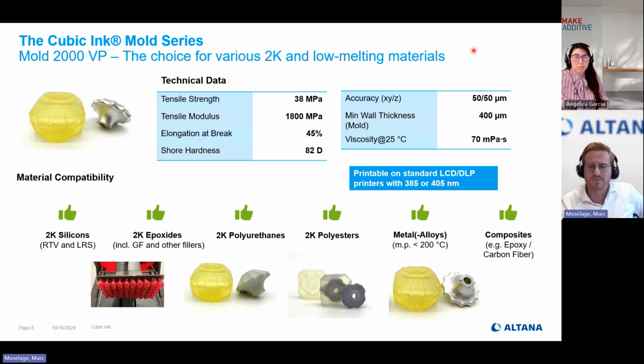Top right, you see some key performance indicators. So the accuracy of the final part, not of the print, is pretty good: 50 micrometers in XY and in Z. The Z accuracy is basically determined by your printer and the layer you print with. 50 micrometers are standard. 100 micrometers sometimes makes sense. Below is a thing some printers can do, some not. But 50 micrometers is really something that can be kept.